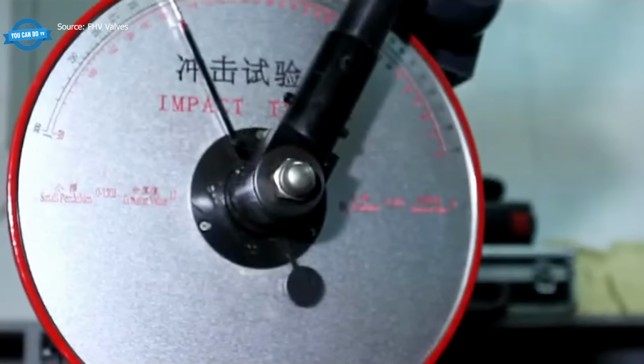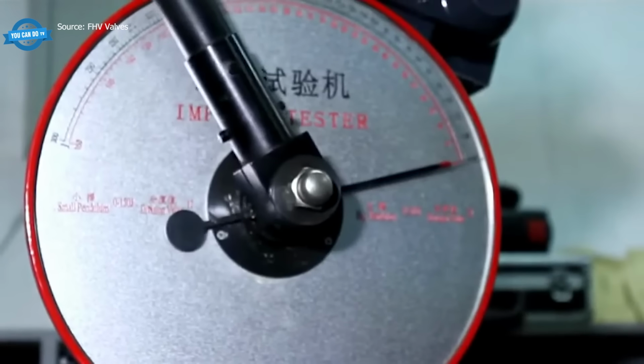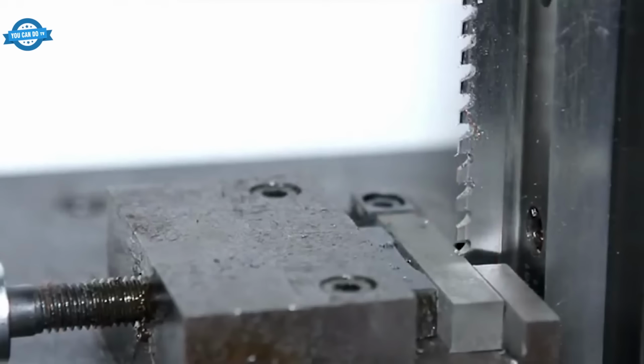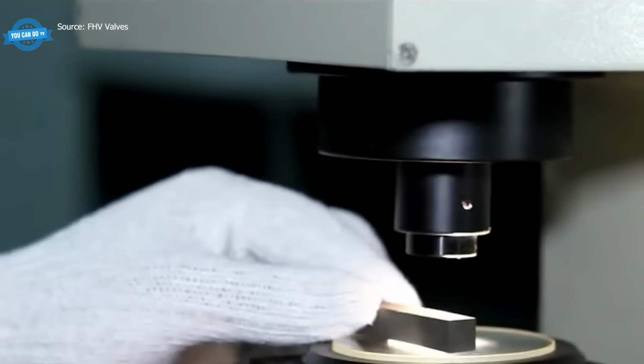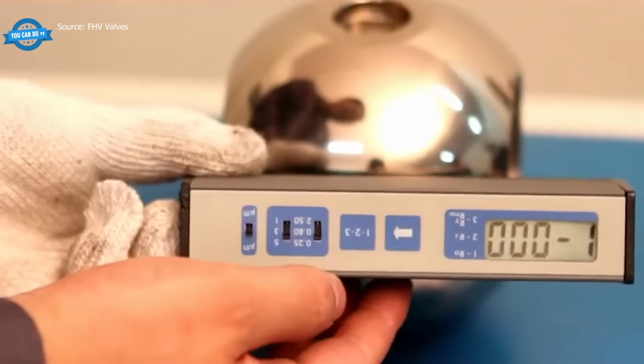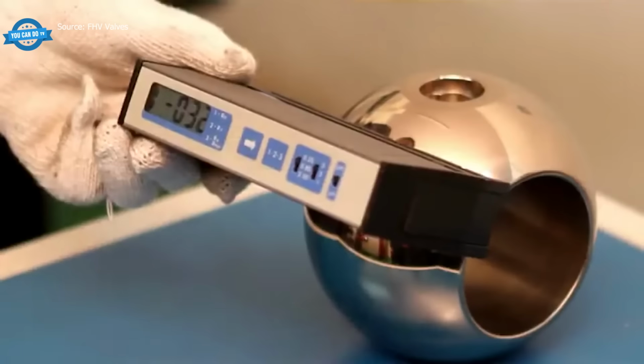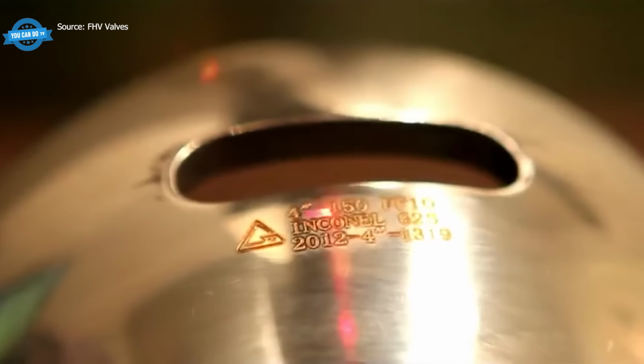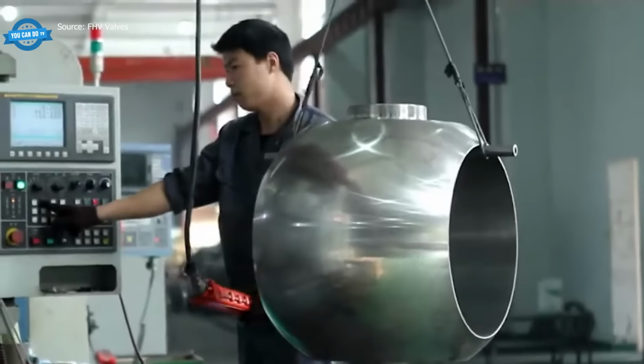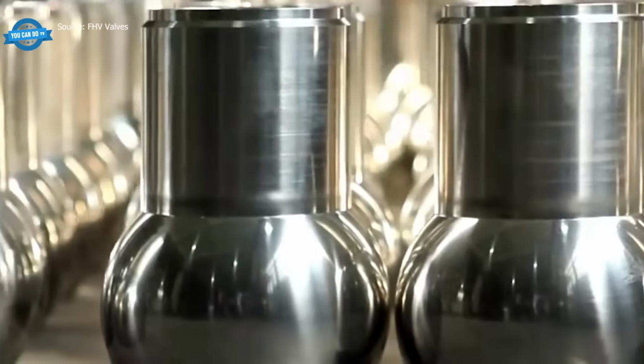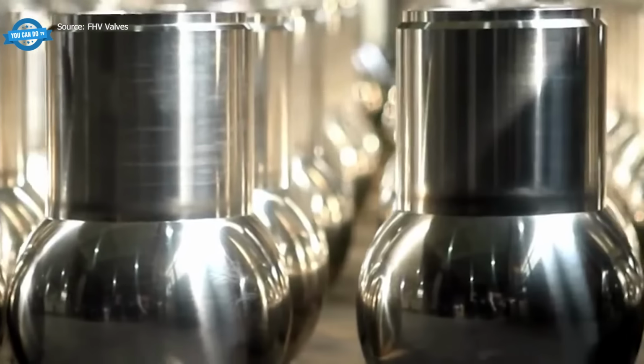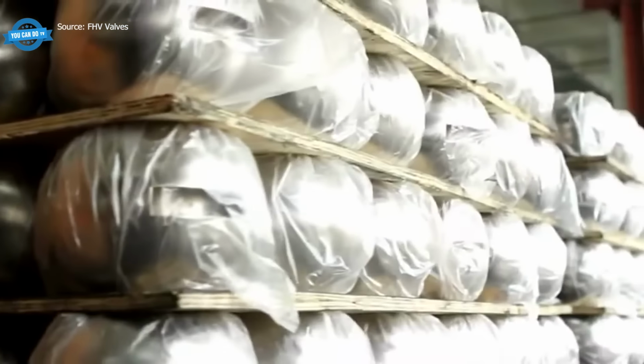Impact testing on a pendulum rig checks the material's resistance to mechanical shock, paired with microscopic structural inspection and tensile testing on a universal testing machine. Surface roughness-hardness measurements follow on digital gauges. Finished components are laser-marked with material codes, including high-pressure alloys like Inconel 625, then verified once more by hand with calipers before shrink-wrapping and palletizing for dispatch.